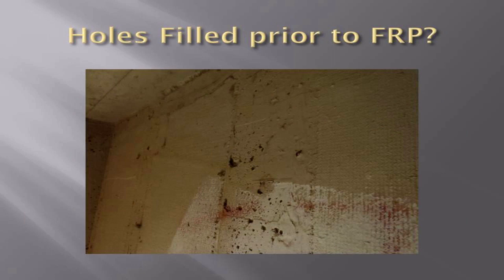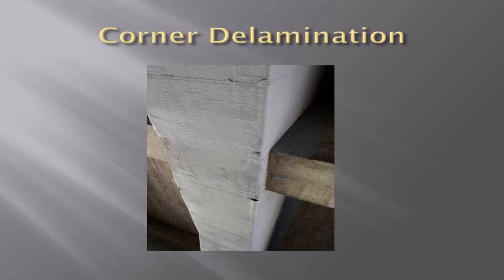Here's another example, just poor surface prep. This is pretty common. Maybe a kink in our fiber, in our shear carbon fiber wrap here. A lot of voids. Corner delaminations. This seems like more of a kind of moderate to major deterioration. As you can see from the ground up, it kind of seems like everything's just fine. The wall of the upper wrap, or most of the U, is still in contact. However, when you have a void in the corner from just the lack of pulling the carbon fiber sheet, therefore the stresses won't transfer between the flange and the web.